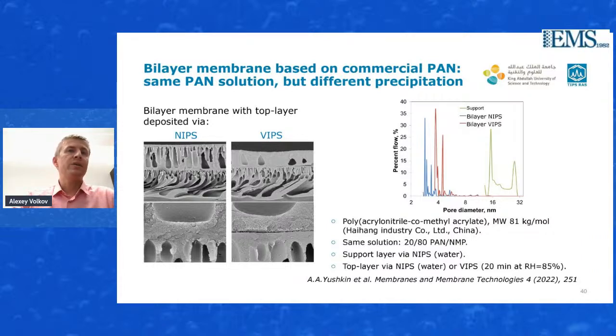As I said before, by using different approaches to casting the top layer, using NIPS or VIPS, we can also adjust the pore size distribution and the performance of the membrane. On the left-hand side, you can see how we can change the morphology of the top layer by applying NIPS or VIPS methods. And on the right-hand side, we can see that the VIPS method usually gives us bigger pore size and NIPS smaller pore size. But the most important thing is that by casting a thin top layer, it's possible to reduce the pore size of the support material itself.